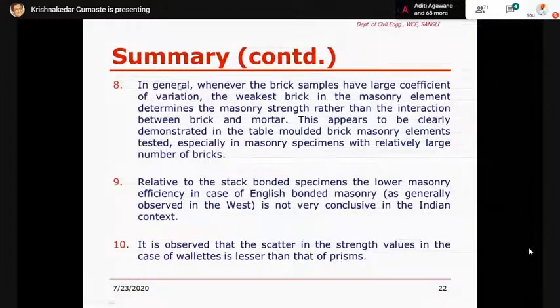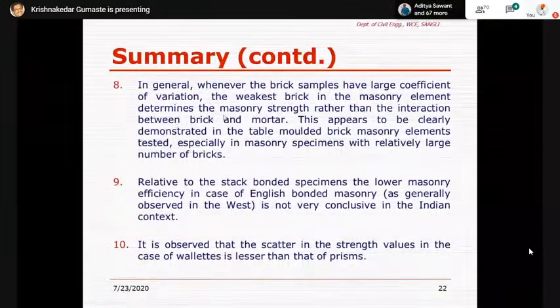In general, whenever the brick samples have a large coefficient of variation, the weakest brick in the masonry element determines the masonry strength rather than the interaction between the brick and the mortar. This appears to be clearly demonstrated in the table-molded brick masonry elements tested, especially in masonry specimens with a relatively large number of bricks.